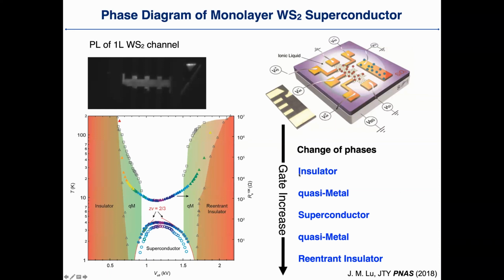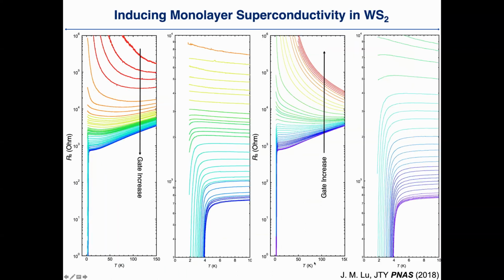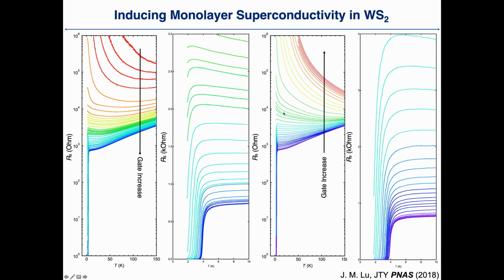But the sequence here starts from insulating without carriers. We have a metallic state, a superconducting state, and then it becomes metal again and becomes insulating again. So what happened there, we can see very clearly. First, from the insulator, we gate with more carriers, it becomes more metallic, and it becomes superconducting, and this is an expansion of that. And then with more gating, it starts from a superconductor, then goes back to the metallic state, and then back to a very insulating state, going to the megaohm range. And in each case, this superconducting state is very well behaved.